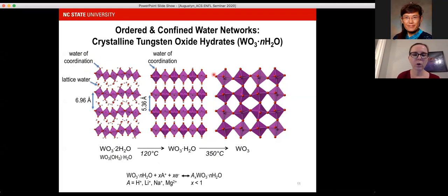Also, for all these materials, they contain tungsten in the 6+ state, and the tungsten is redox active, so it can undergo electrochemical charge transfer with a variety of ions. But what I'll focus on specifically in this presentation is the insertion of protons, because we thought there could be interesting interactions between protons and these confined water networks. So that was our hypothesis starting out.